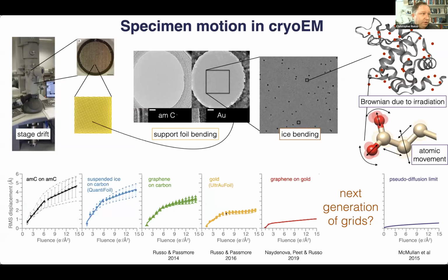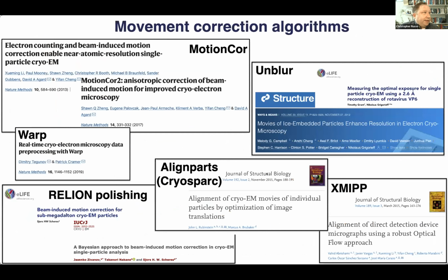So how do we get from here, which is where we were in about 2014, down to here? Well, we tried adding graphene to these, and that did help, but it still didn't bring us all the way down to this theoretical limit set by the diffusion of the molecules. And so one thing you can do is, of course, use movement tracking software. And there's been an increasing number and sophistication of algorithms that have been published and developed in order to try and track the movement of the particles and then compensate for it in post.